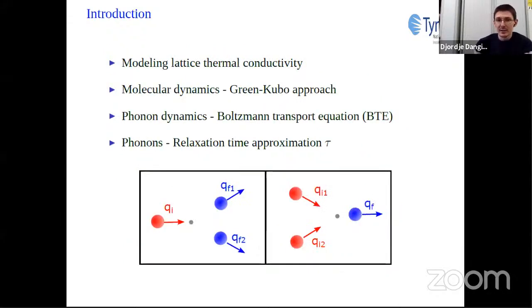There are many ways of calculating lattice thermal conductivity from first principles. For example, one might run molecular dynamics simulations and then use Green-Kubo relations to connect fluctuating heat currents and the lattice thermal conductivity coefficient. Alternatively, one might use phonon dynamics, or some people call it lattice dynamics approach, to extract the relevant phonon properties, then use those phonon properties in the Boltzmann transport equation, usually in relaxation time approximation, to extract lattice thermal conductivity. Boltzmann transport equation sees phonons as a gas of weakly interacting particles that carry heat between scattering events that happen every phonon lifetime.